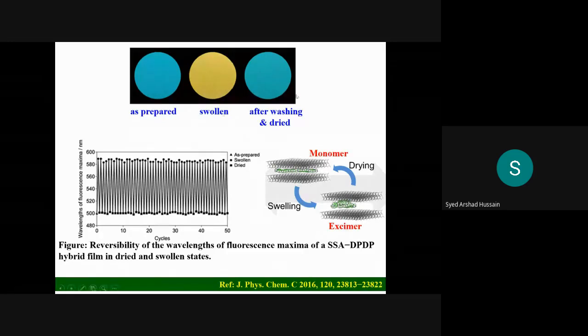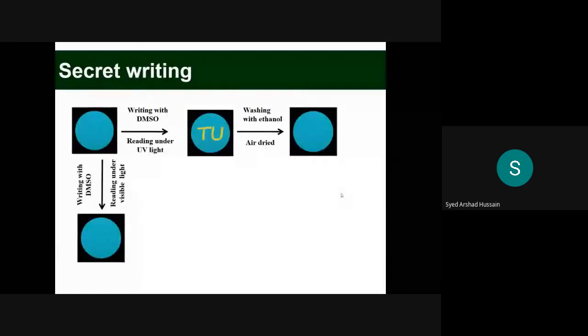And we studied this process. You see, this is the repetition of color due to drying and swelling, and we have seen that this is a reversible process. Here it is shown schematically. In the normal process, this is as-prepared, one molecule within the clay layer. But in swelling, when we put DMSO, the gap between the layers increases, so two molecules stack together and form an excimer. Accordingly, the fluorescence property changes, with a longer wavelength band when exposed to UV torch.